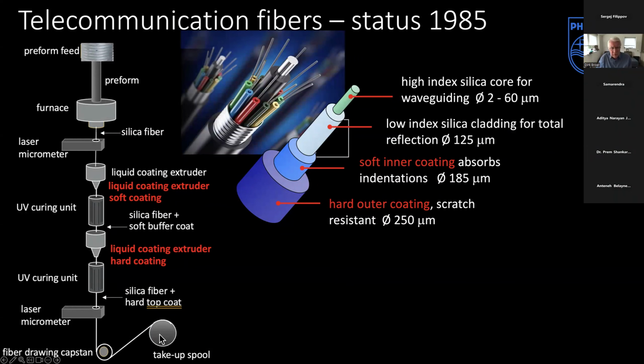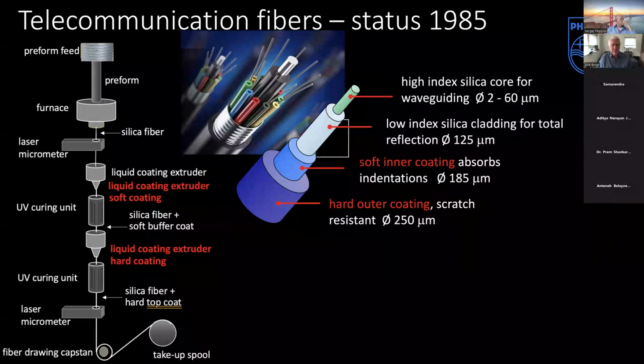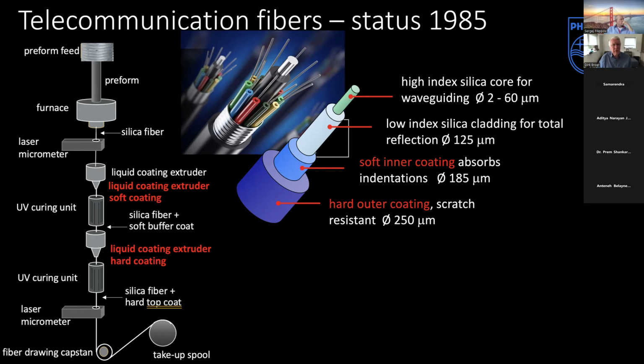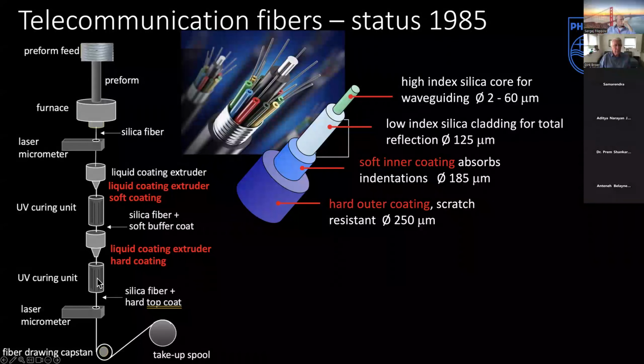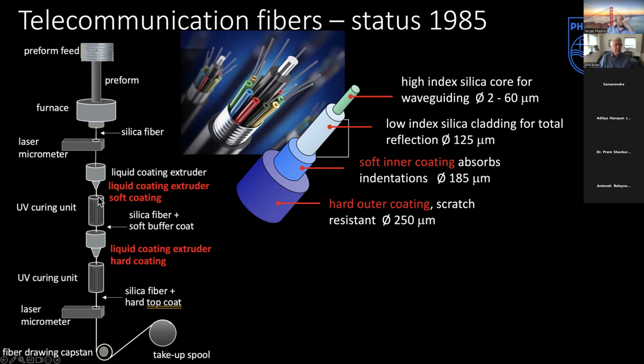Now, quartz is intrinsically a very strong material, but it has one problem. If it comes in contact with any other surface, surface scratches, surface flaws are easily formed, which reduces the strength enormously. So it has to be coated online during the fiber drawing process with polymer coating materials. For that reason, people were using UV polymerization, because the material must have a low viscosity, as the drawing rate is very, very high. It can be up to 10 meters per second, and the coating should be cured very fast.